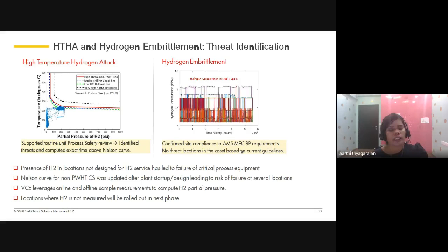Basically, it affects the granular properties of the material, or a combination of all these factors I explained. Now, this mechanism called HTHA has been encountered in carbon steels mainly, with and without what we call post weld heat treatment, because after post weld heat treatment, the material structure of the carbon steel becomes slightly toughened and hence less amenable to HTHA. But if it's not post weld heat treated, it is highly susceptible to these kinds of attacks. Now, HTHA is challenging to inspect because it's not something that happens every day in our asset life, and it is very catastrophic. So it's good that it doesn't happen every day, but even though it is a rare event, there is a lot of industrial data around this.